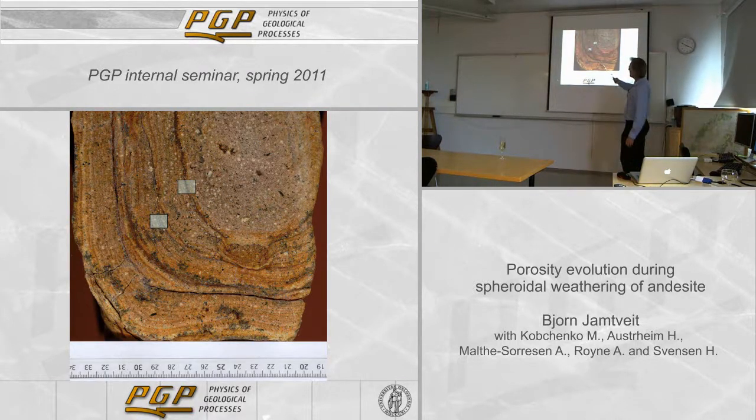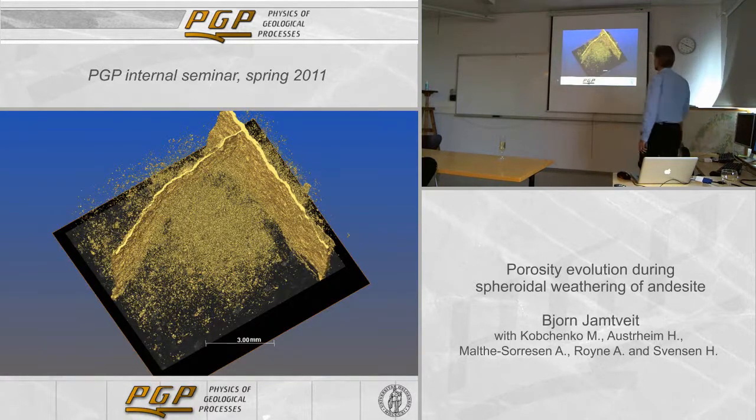And then if you go out where you can actually see a microscopic fracture, and of course we can also map it out in CT scans, this is one of these common skin fractures that typically span out one layer from the main core stone. And there is a little perpendicular fracture to that as well, and this in the middle here is porosity in the matrix outside the area where you have microscopic fractures. And it looks like a lot of porosity here too, it's less than 0.5% porosity, and all these pores are very small. There are no big pores, so these big pores, 100 microns plus, you don't see in the rocks when it has undergone microscopic fracture formation.